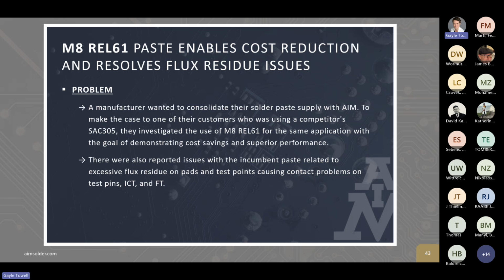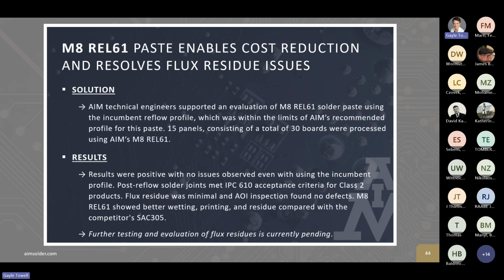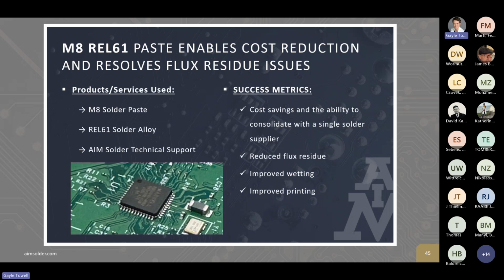They had had some issues with the incumbent paste, with excessive flux residue on some of the pads and test points. So they tried out REL61, ran it on 15 panels, a total of 30 boards. And the end result was they had no issues, even without changing the reflow profile from what was already programmed in. And the joints met IPC criteria, and the residue was minimal, and AOI inspection found no defects. The REL61 paste showed better wetting, printing, and residue compared to the competitor SAC305. So end result was they were able to demonstrate there would be cost savings because it's a lower cost alloy. Again, reduced flux residue, that was no longer an issue, and they saw improved wetting and printing performance.